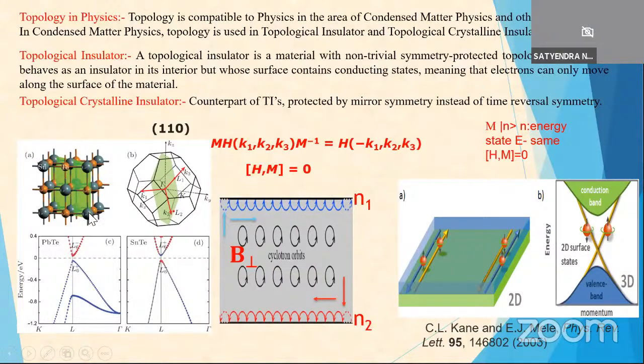This is the 110 surface state in SnTe present predominantly, and all the other surface states, 100 and 111, are also here. But in all the surfaces, this is a topological crystalline insulator predominantly in the system. This is the Brillouin zone counterpart here, and this is the gamma point here.